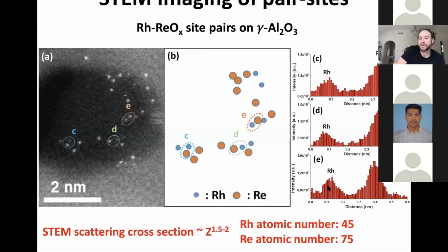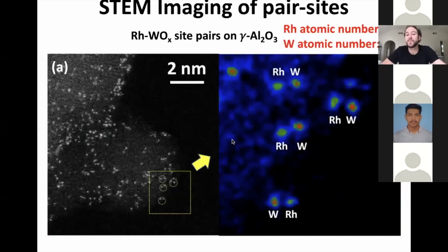And we could then compose this and say, we didn't perfectly make pair sites because there's other things happening here, but we did make a lot of pair sites, and we can begin to imagine that these will have additional catalytic functionalities than you would have with just the rhodium sitting there by itself. We've taken this a few steps further and gotten better and better at this, and you can see now we can make very nice pair sites of rhodium and tungsten, where we're using the same site-selective deposition of rhodium right next to tungsten, so that we can really push this towards increasing functionality.